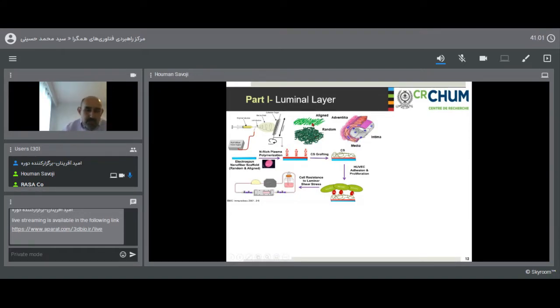So we did the same thing. We developed aligned or random fibers for the first layer, for the intimal luminal layer, and we used PET. Since the surface of this material is inert, we used plasma polymerization to coat them with the primary amine group, and then we grafted chondroitin sulfate. Chondroitin sulfate is a sugar, is one of the components of our ECM or extracellular matrix. It's biodegradable, biocompatible. So we added chondroitin sulfate, and then we studied the effect on cell adhesion and proliferation in a static culture, and also we exposed these cells to shear stress similar to the shear stress in our coronary artery in a dynamic environment.